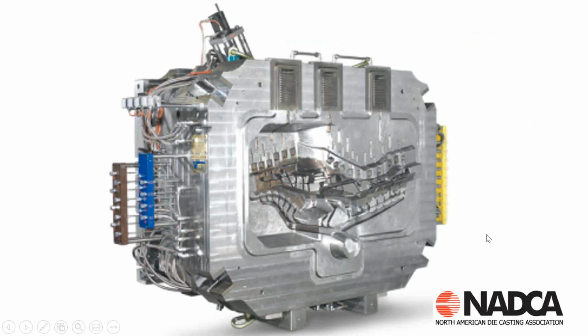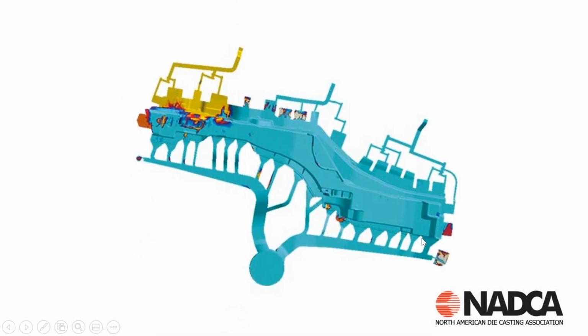So let's examine what that is. Here's a die cast die. We can see the part impression here in the center with the runner system and the gate. So we're gating across the short distance. We have multiple vacuums, and we have a seal that goes around the perimeter of the casting. So we gate the entire available distance, and we gate the short direction. This is typical to structural die castings today.